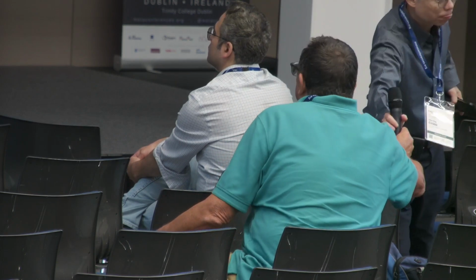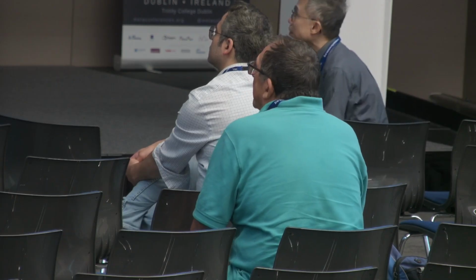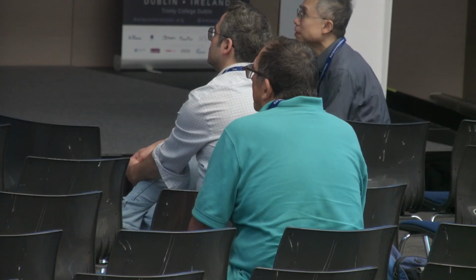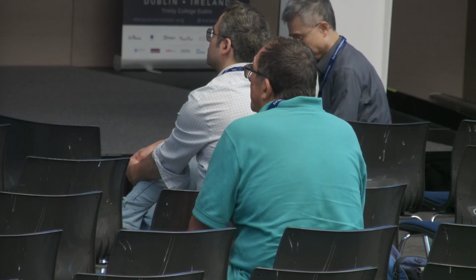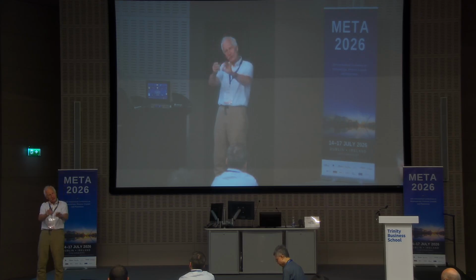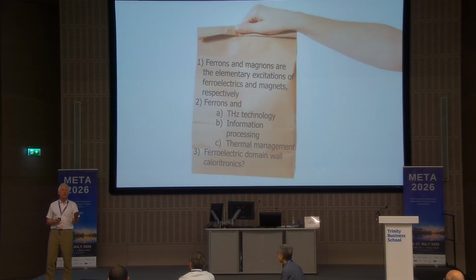Yes. Okay, the first question is indeed sort of among these different ferroelectrics, the displacive ones are the most common. So there the phase transition occurs by so-called soft optical phonons, which go from a finite energy to zero. In this case, the amplitude becomes large and you get the structural phase transition. Now, below the phase transition, you have something which corresponds to this optical phonon, and that is what we call a ferron. We call it a ferron because it has many properties which have up to now been completely neglected.